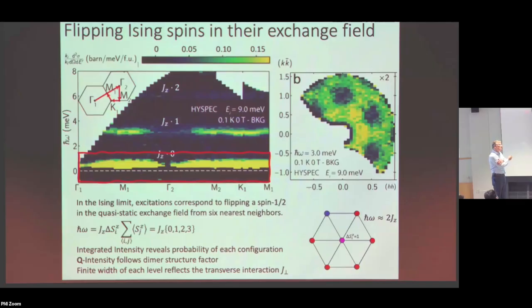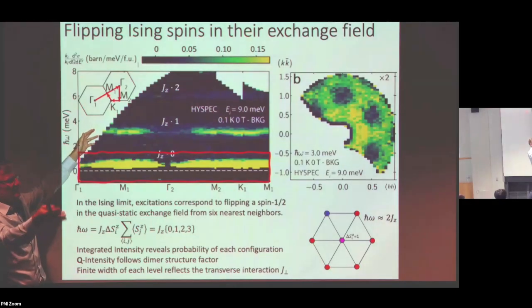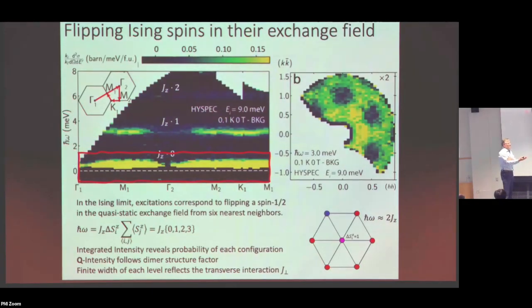Would you get maybe even sub bands with nearest neighbors constantly? Or is it too far away? That's a very interesting point. You would in general expect that. And we have another compound where that comes into play that's a more complicated situation. But what happens in this compound is that the next near and third near neighbor interactions are extremely weak and much weaker than the transverse term. So that means that the broadening of these bands, which is governed by the transverse terms, is beyond the contribution from the further neighbor interaction. All of that is a lovely aspect of the system. It really is focused on the transverse quantum fluctuation generating part, but not the complexity of the further range interactions.